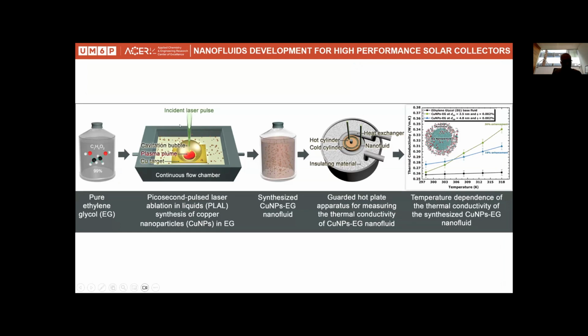We have done some research, taking copper, and we have done ablation of copper in ethylene glycol, even in silicone oils. We use our systems, as you can see with me here. This is the temperature, because you have to measure the thermal conductivity at different temperatures. If I'm using these nanofluids in CSP systems, for example, they work at different temperatures. They don't work at room temperature. One should find out the impact of temperature on the nanofluid.